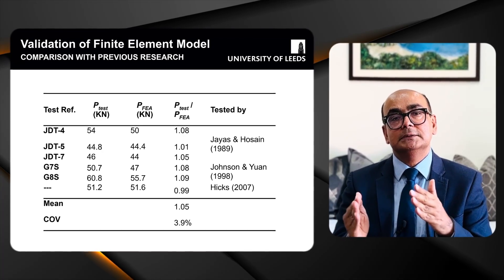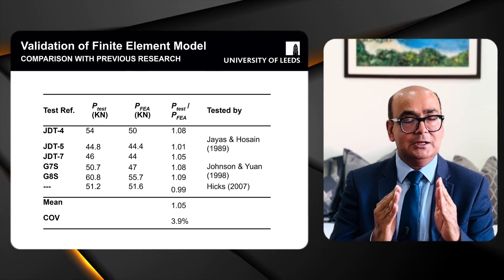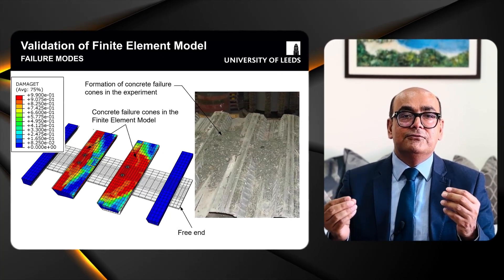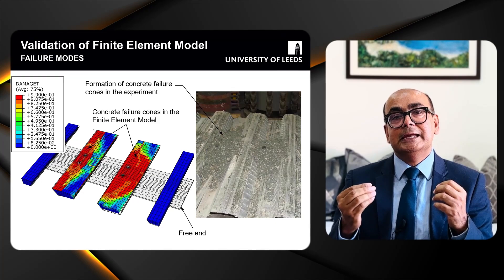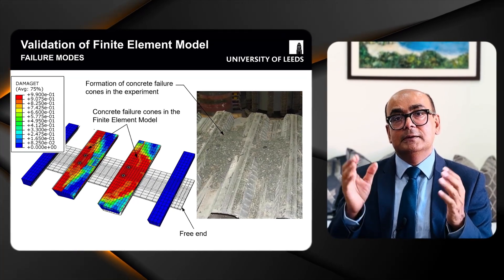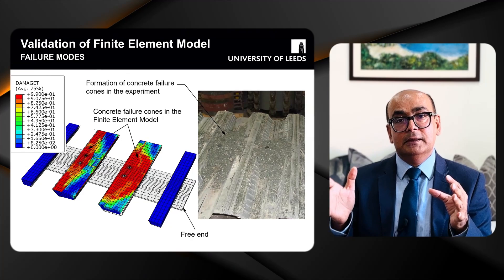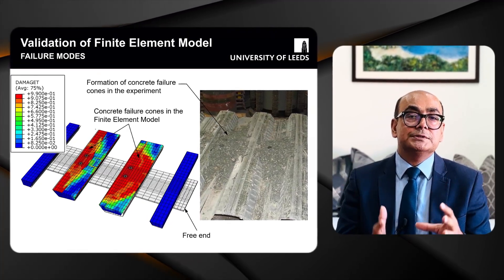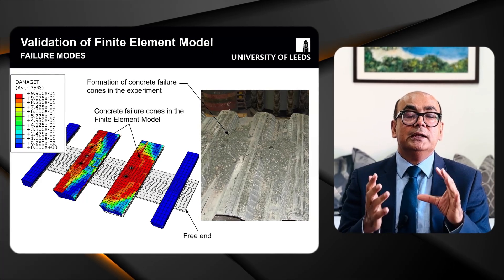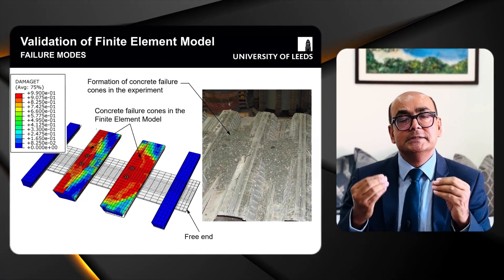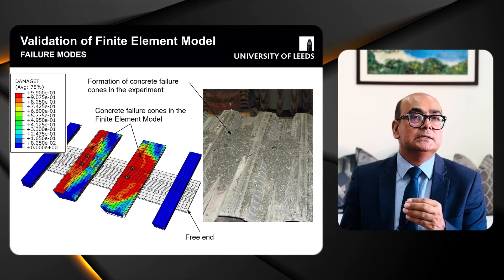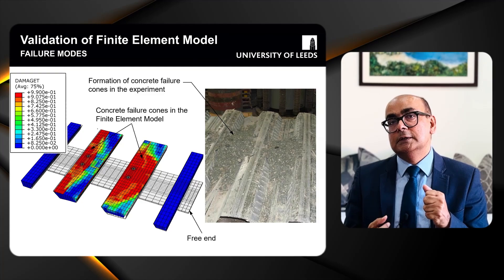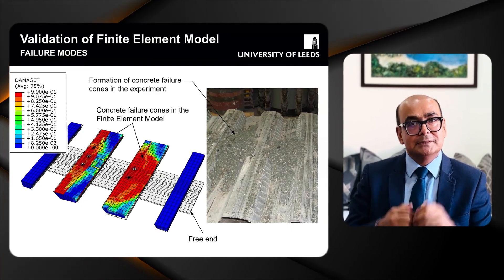Comparing with various experiments, results from the finite element model and experiments match very closely. The failure modes are particularly interesting: the red colors indicate cracking, and on the right side you can see the experiment. Around the two shear studs it can be observed that cracking in the finite element model occurs in the same way as in experiments. This was a really important takeaway from this research.